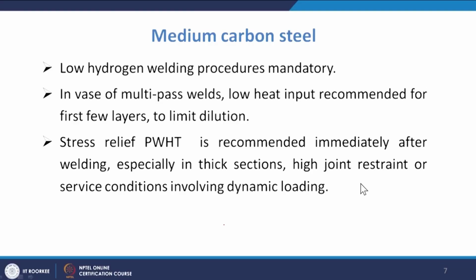So next, for medium carbon steel, low hydrogen welding procedures are mandatory. In multi-pass welding, low heat input is recommended for the first few layers to limit the dilution. Okay, stress relieving post-weld treatment is recommended immediately after welding, especially in thick sections and high joint restraint or service conditions involving dynamic loading.